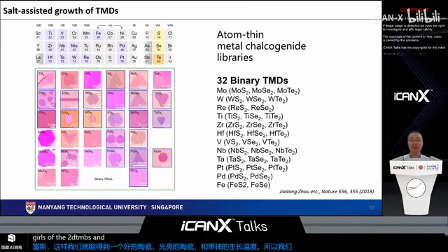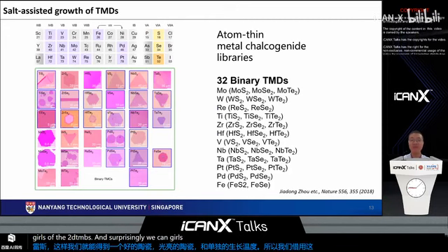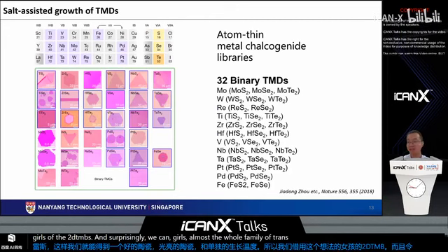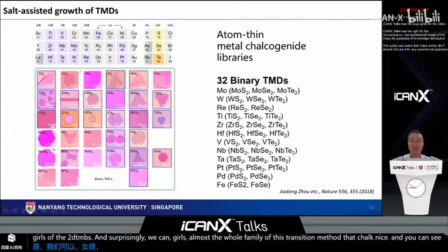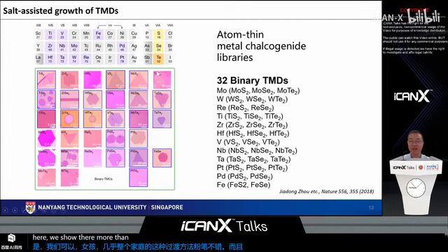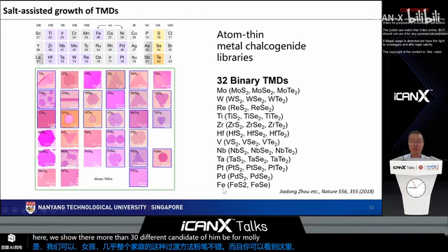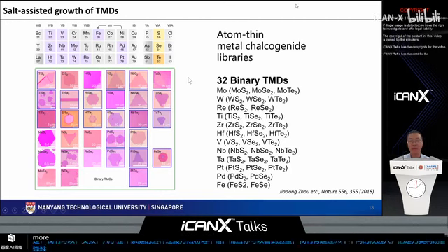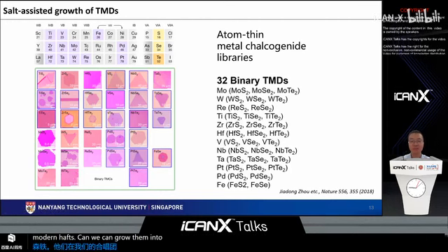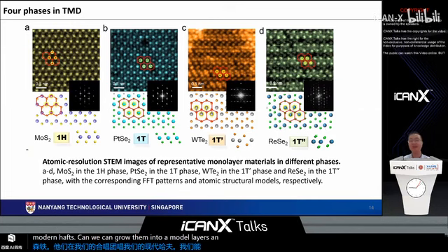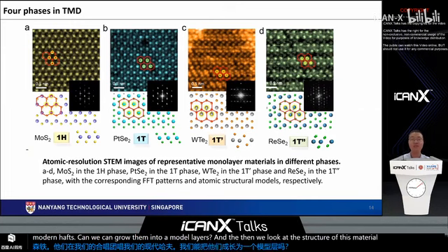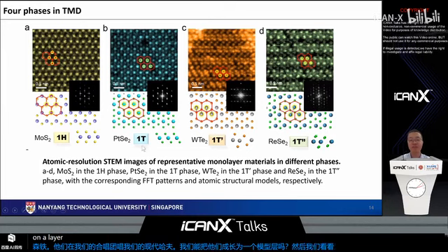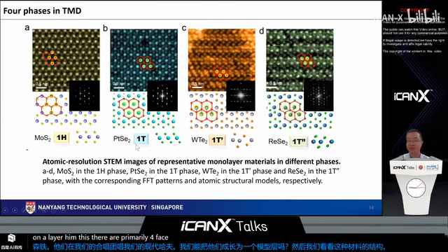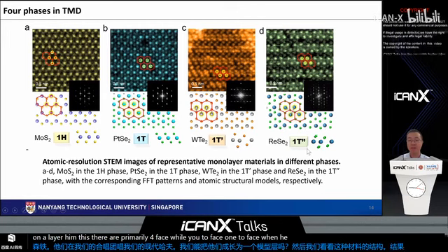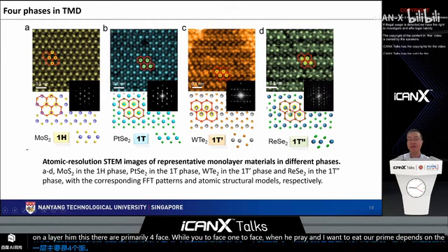And surprisingly, we can grow almost the whole family of these transition metal dichalcogenides. As you can see here, we show more than 30 different candidates of TMD, from moly, tungsten to iron. And for most of them that are quite thin, more than half, we can grow them into monolayers. And then we look at the structure of this material. It turns out the monolayer TMDs have primarily four phases: 1H phase, 1T phase, 1T prime, and 1T double prime, depending on the position of the ions.